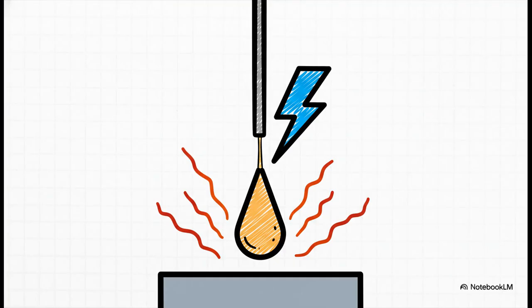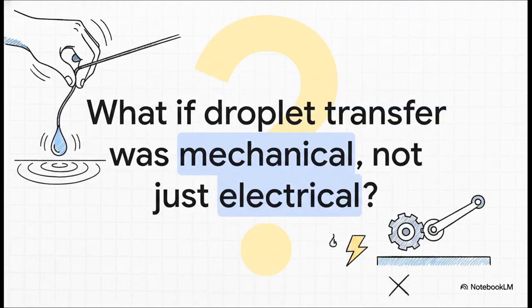See, even with all the advanced pulsing, there was still this one little physics problem they couldn't quite crack. In MIG welding, you've got a wire that's continuously feeding into the arc. To get a droplet of molten metal to actually detach from the end of that wire, you usually need one final surge of current to kind of pinch it off. And that little surge adds extra unwanted heat. And that led to this brilliant question, the genius idea behind the next technology.